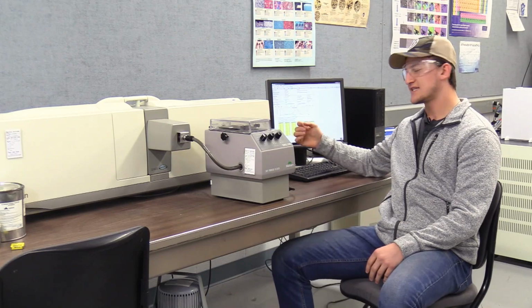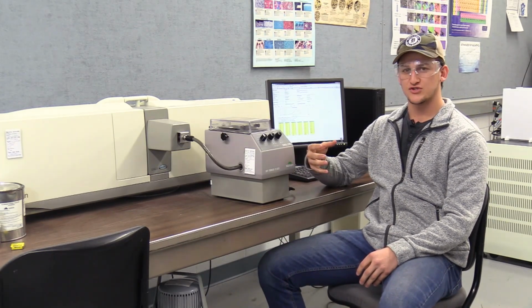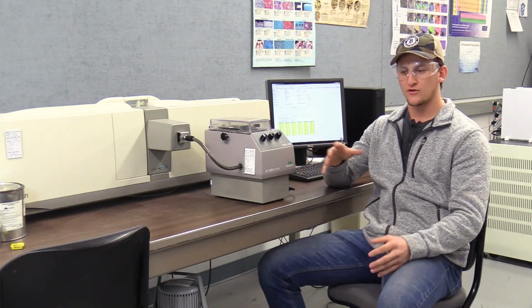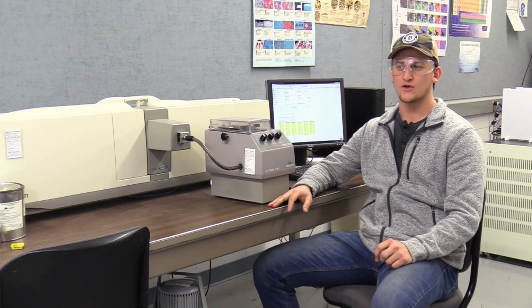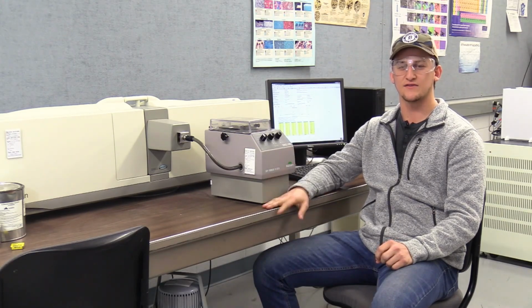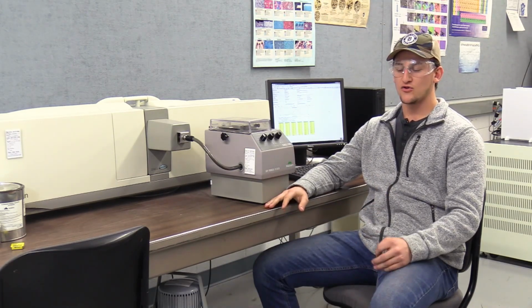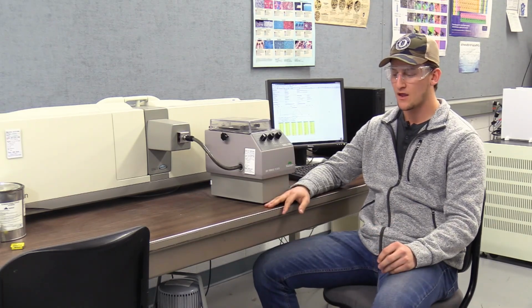So here we see it's between 10 and 100 micron. What this is telling you is that the particles you just tested were all between 10 and 100 micron, with a little bit of variation in between. So this gives you an idea of the size of particles you're going to be working with. When we look at different things in the video later on, you'll know what you're working with to give the desired results you're ideally targeting in making your powder products.